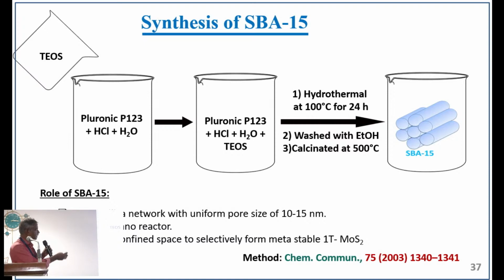So we prepared this material based on our Chem. Commun. paper in our laboratory, because we need more than 5 to 10 grams per single batch. So we need to reproduce the same results. That means your SBA-15 should have identical properties, so you have to have your own methodology to produce large-scale SBA-15 in your laboratory. The very important thing is the first step. We prepared a TEOS-based method, where we use Pluronic P123, HCl and H2O, then hydrothermal treatment at 100 degrees for 24 hours, washing with ethanol and calcination at 500 degrees.